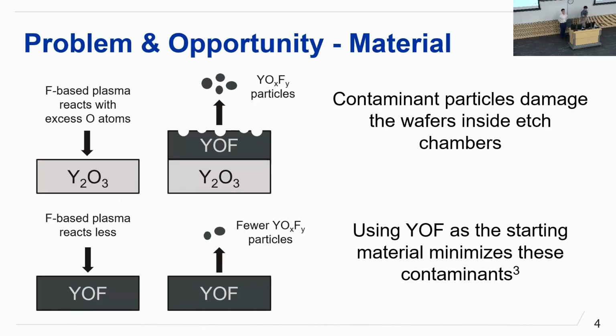So a common material being used today in these dry etch chambers is yttria. And when yttria reacts with a fluorine-based plasma in these dry etch chambers, it creates a thin YOF layer, or yttrium oxyfluoride. And with this interaction, YOF particles will fall off the coating and can contaminate the wafer inside, which is not desirable when you have these multi-billion dollar industries that rely on these wafers to be pumped out. And so a different perspective is looking at YOF as the coating itself.